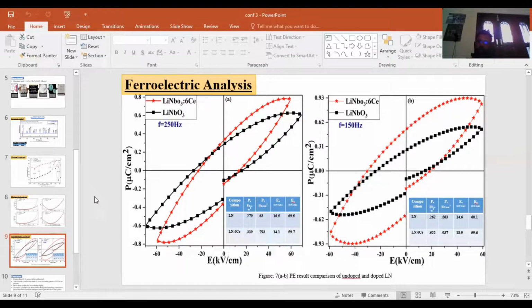But for my work, at frequency 250 hertz, for the doped sample it is 0.8 microcoulomb per centimeter square, and for the pure it is approximately 0.6 microcoulomb per centimeter square when the applied electrical field was 60 kilovolt per centimeter. And at 150 hertz, it is approximately 0.93 microcoulomb per centimeter square for cerium doped lithium niobate, and for the pure one it is approximately 0.6 when the applied electrical field was 60 kilovolt per centimeter.